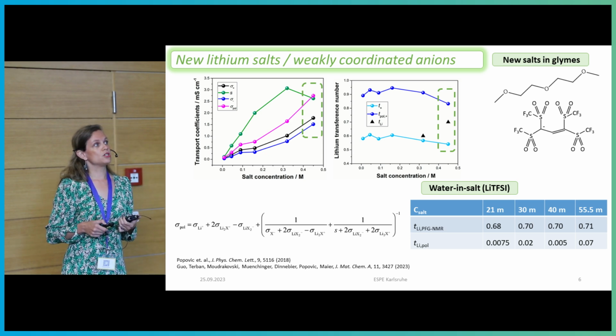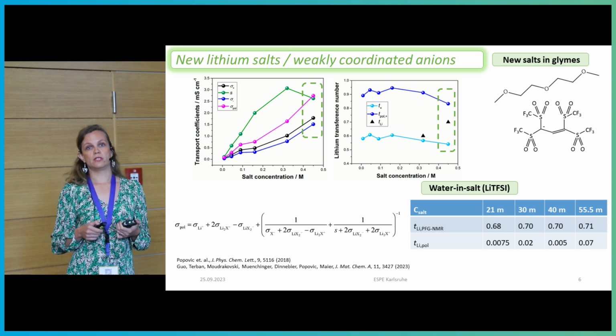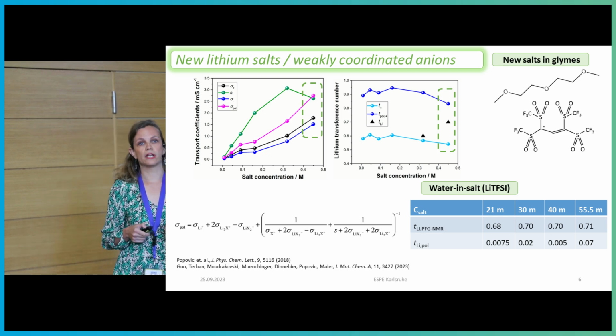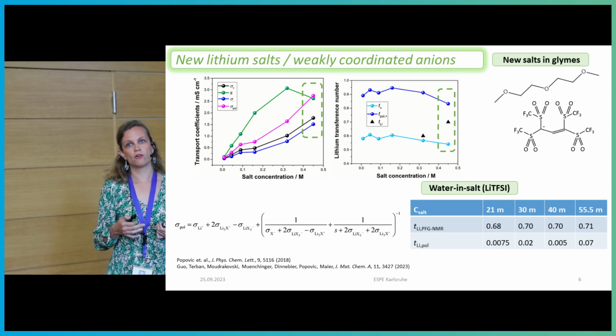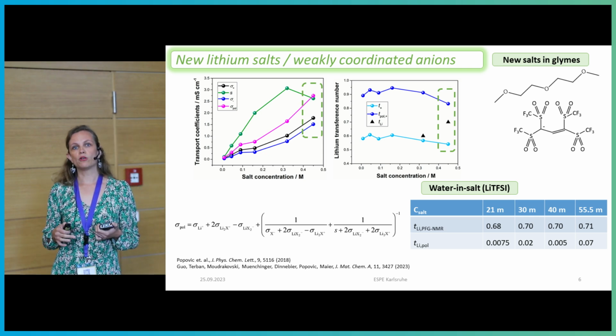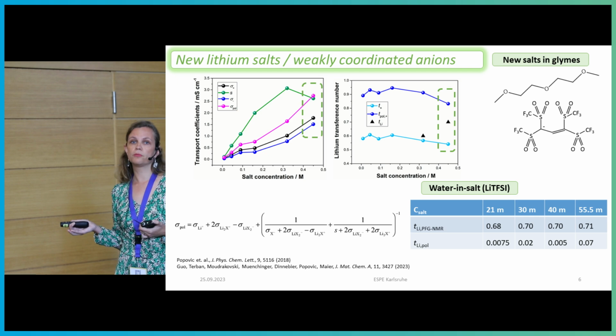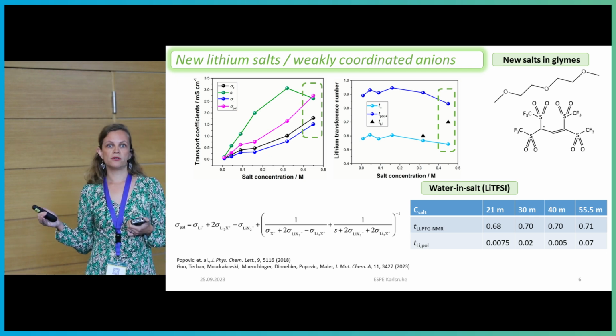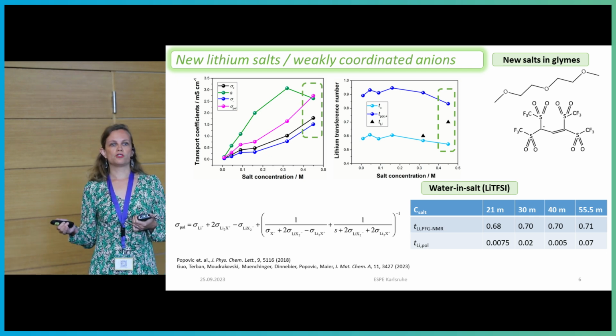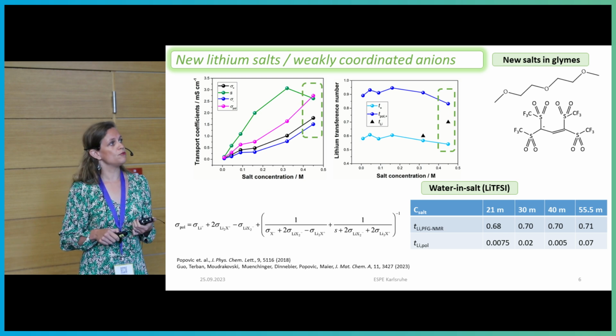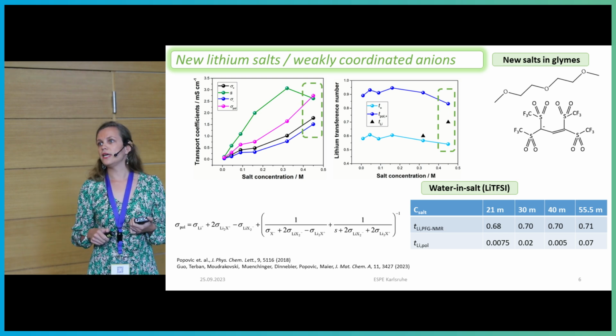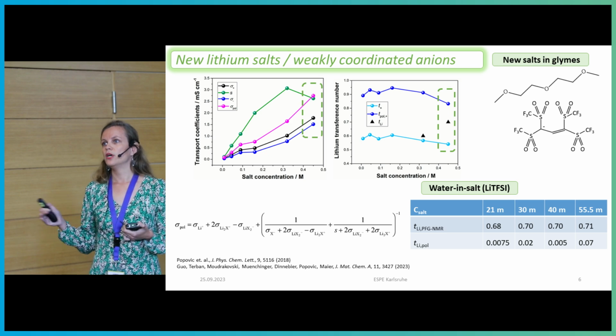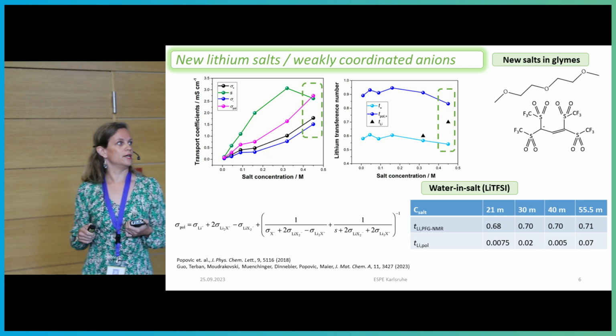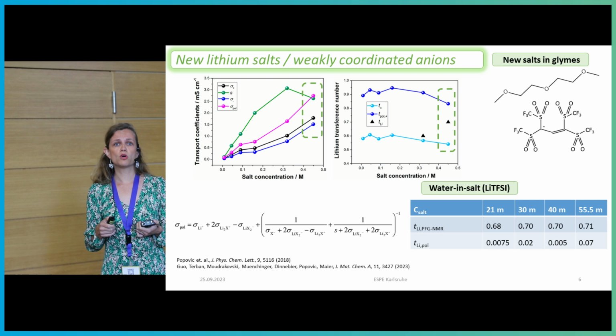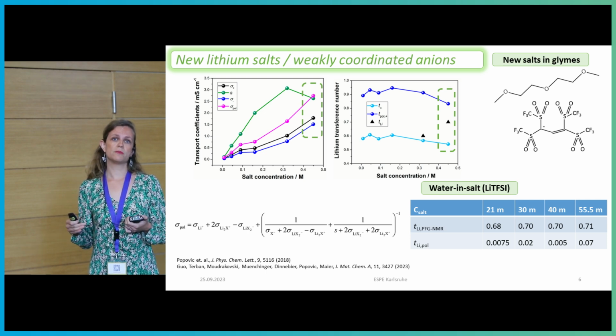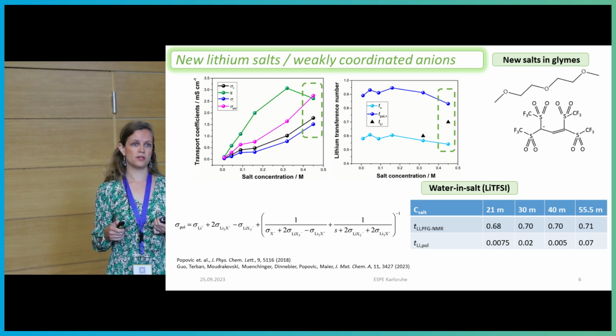The other situation is a very extremely concentrated electrolyte, which is a water-in-salt electrolyte with lithium TFSI, so a very model system. And I don't know if you have been following that field, but there have been speculations that there is very fast lithium conduction and very high transference numbers. And if you look at the PFG NMR data, they do suggest that lithium moves quicker than the anion. So we took upon ourselves to look into the electrochemistry of these materials and try to actually measure the transference number.